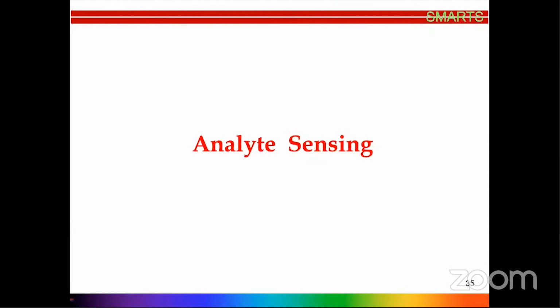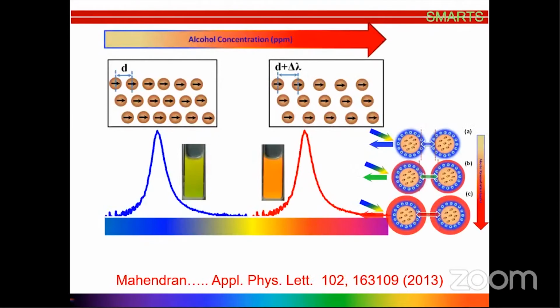And these fluids can also be used for sensing applications. The technique is very simple. When it comes to detection of analytes, what we need is sensitivity and selectivity, obviously, and the simplicity of the technique, and it should be cost effective. What we have demonstrated here is, you create an array of these particles. This can be done very easily with a magnetic field, and the magnetic field strength required in this case is not very high. It's of the order of 80 or 90 gauss. This can be generated very easily with a toy magnet also.